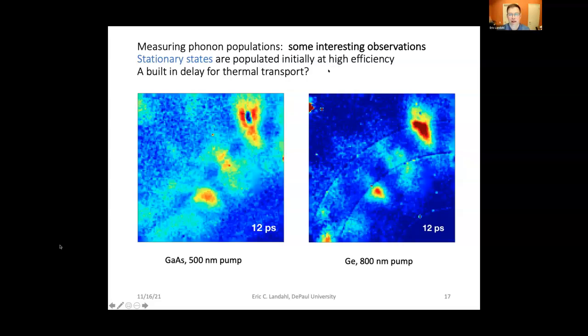So you have to start to ask, is this a built-in delay for thermal transport? Are we actually populating phonons at the zone edge very effectively, which then don't move very fast? And in fact, they do hang out in these experiments quite a while, waiting for some sort of anharmonic decay to happen. And that's observable in both materials.